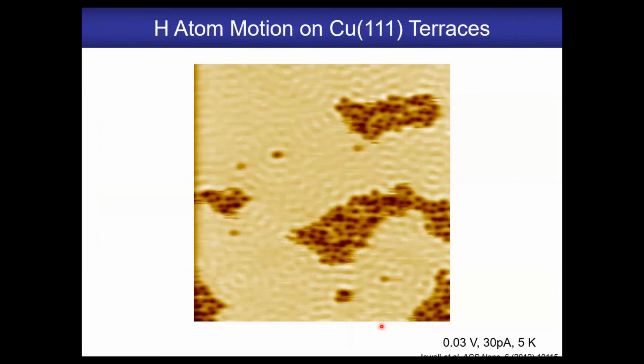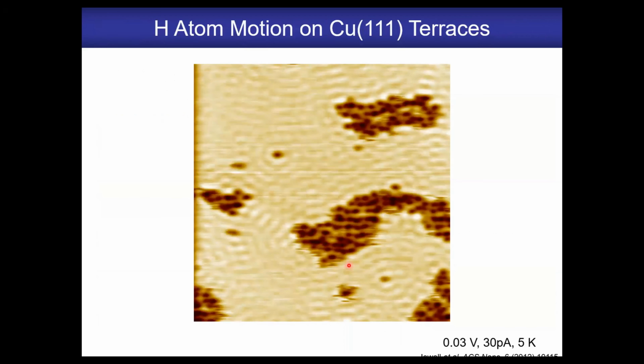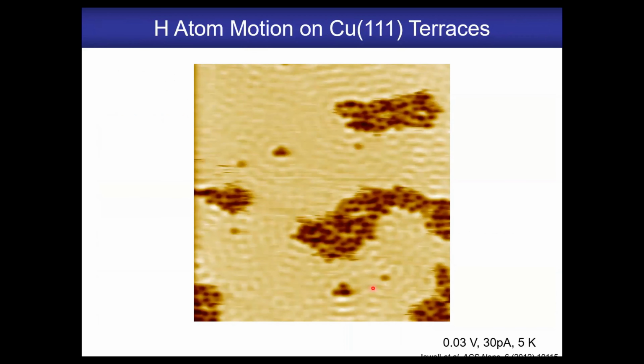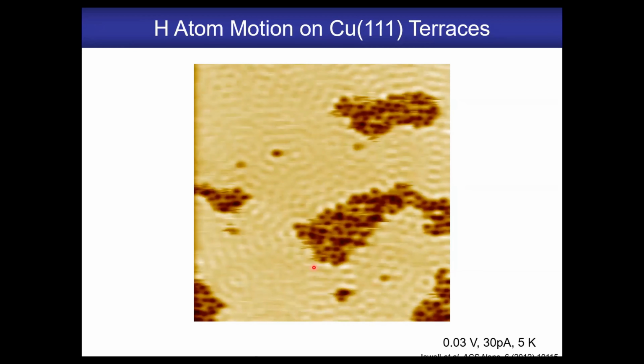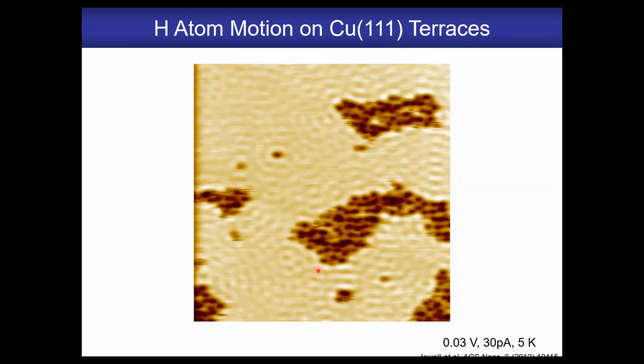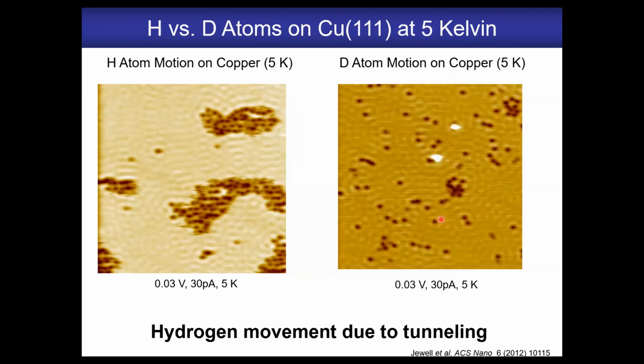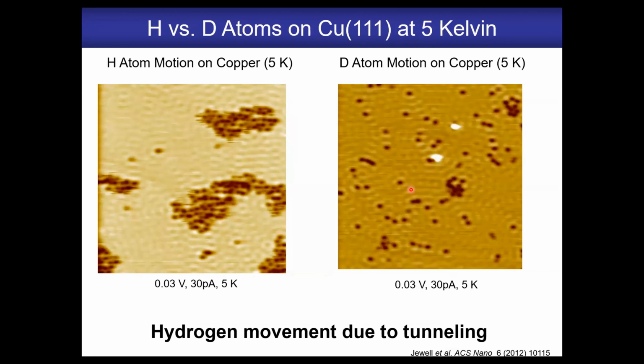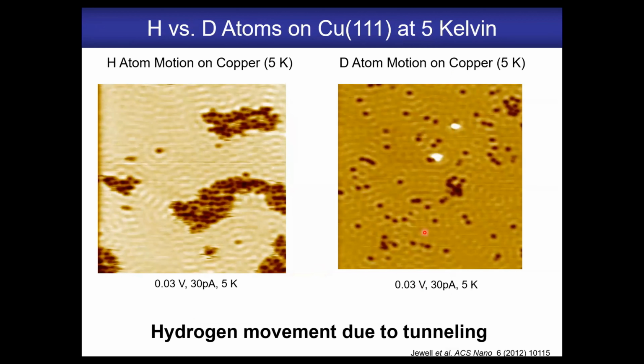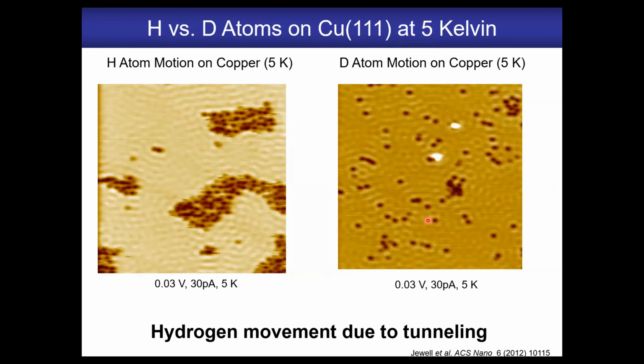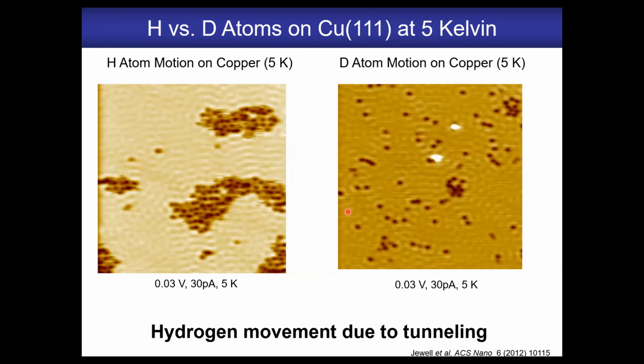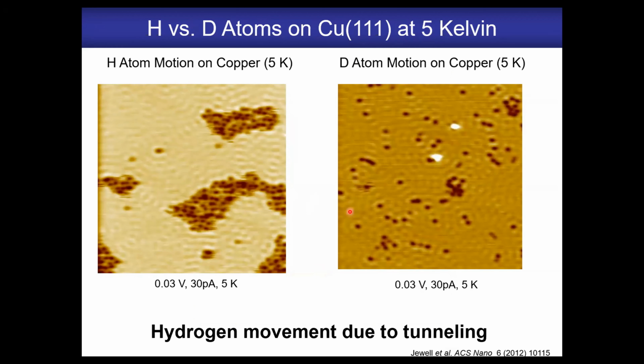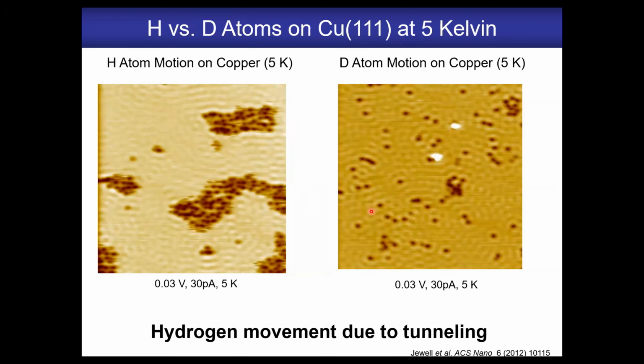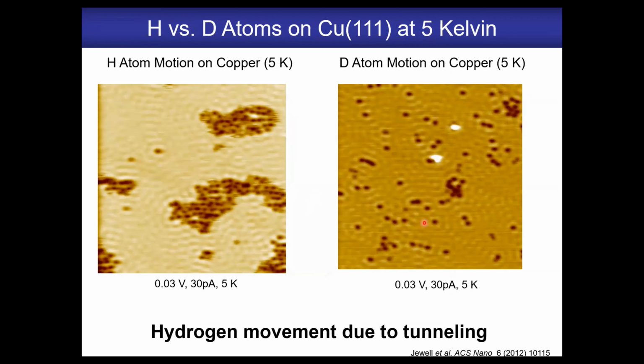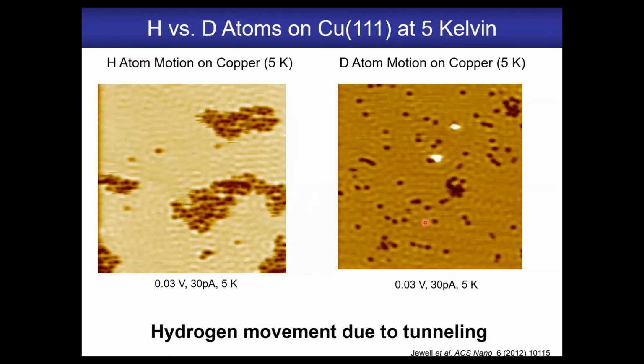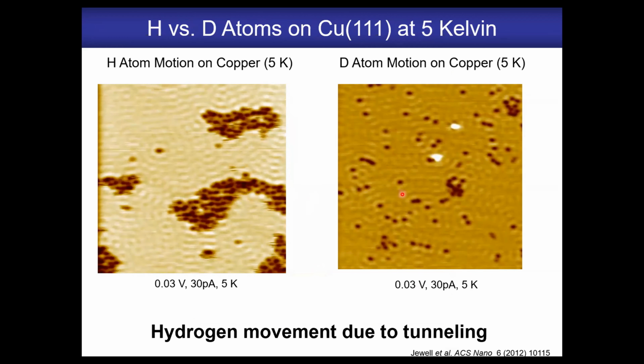And we can image the dynamics of these, and you can see the fast diffusion of the hydrogen atoms on the copper surface here. And it turns out that's actually mediated by quantum tunneling through the diffusion barrier. Because if you do the same experiment with deuterium atoms, you can see on the right here, the rate of diffusion of the deuterium atoms on the surface is a lot slower. So I hope here I've convinced you that just by depositing molecular hydrogen on these single atom alloys and then cooling all the way down to 5 Kelvin where we can image the hydrogen atoms, they have dissociated at the palladium site, but then spilled onto the copper surface where they're weakly bound.